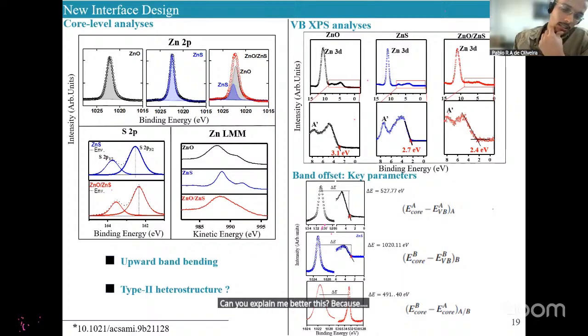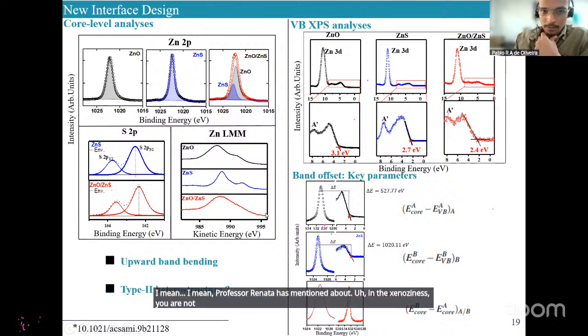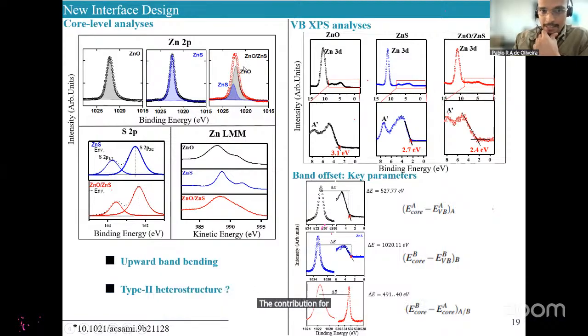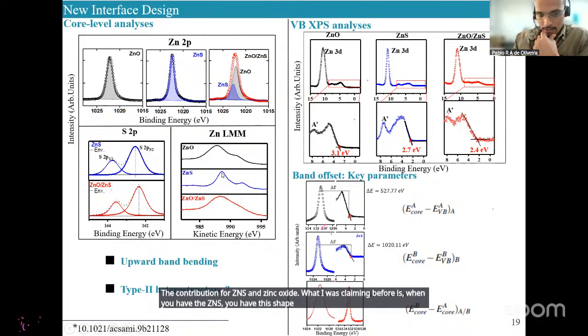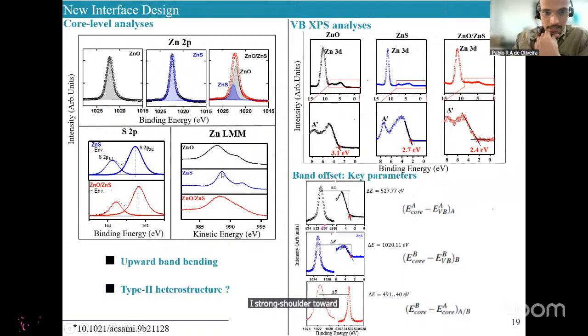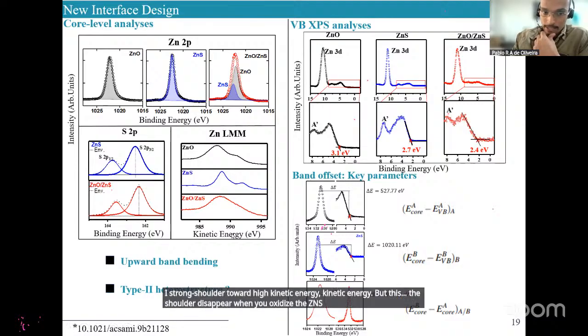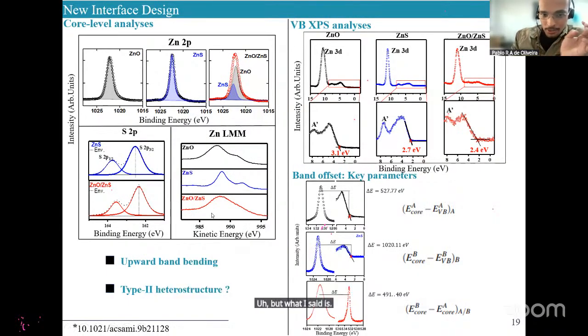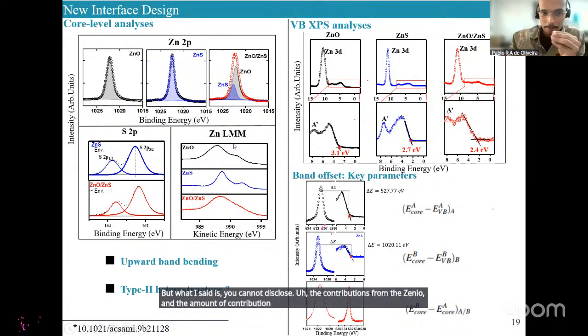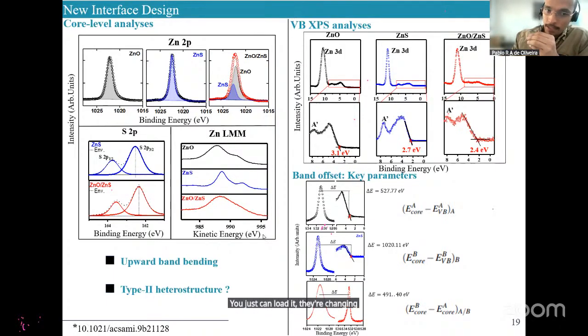Professor Renata mentioned that in the ZnO-ZnS you are not able to deconvolute the contribution of ZnS and zinc oxide. What I was claiming before is that when you have the ZnS, you have this shape with a strong shoulder toward high kinetic energy, but the shoulder disappears when you oxidize the ZnS, obtaining the ZnO-ZnS. Of course you have the hybrid interface, but you cannot disclose the contributions from the ZnO and the amount of contribution from ZnS. You can only note the change in the shape of the peak. That's what I said to Professor Renata.